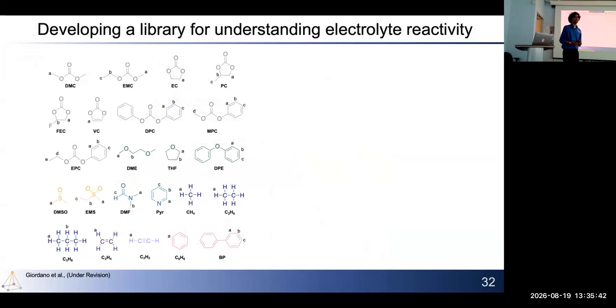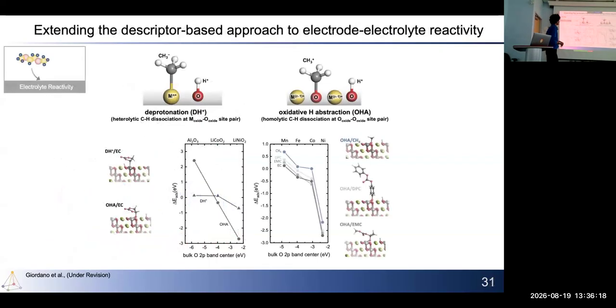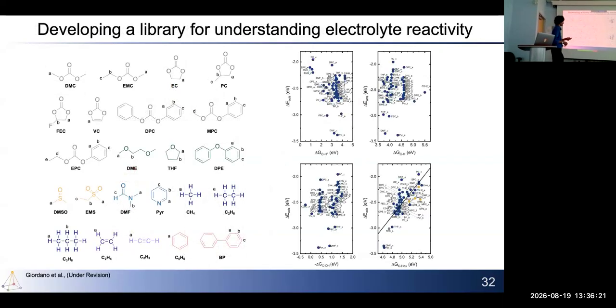Now the question is, which electrolyte should we be using then? So what we did was develop a whole library of electrolyte molecules. This is an interesting experiment because in the previous two studies, we wanted to change the catalyst surface itself, the chemistry and structure of the layer. But in this case, we wanted to play around with the electrolytes, the molecule that is reacting, figuring out how to optimize that for a given surface. We tested the reactivity of these 30-odd compounds on the oxide surfaces, and we found a very curious result.